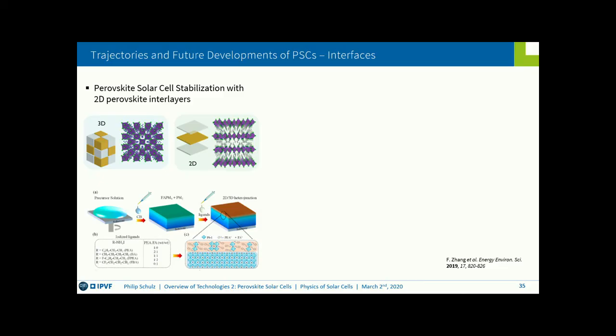Now, the last two points I wanted to make are really perovskite solar cell stabilization with 2D perovskite interlayers. So you can actually start off with a 3D perovskite that has a PbI2-rich surface. And now you can start introducing these long chain molecules in order to make an interlayer that follows the 2D structure.